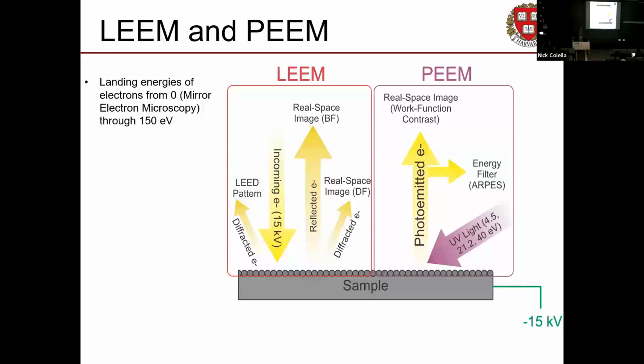And the way that happens is the electron beam is coming in at 15 kilovolts. Sample is also at 15 kilovolts. So as the electrons approach the sample, they slow way down and just barely tickle the surface, and then head right back out again up through the same lens. And that's LEEM.